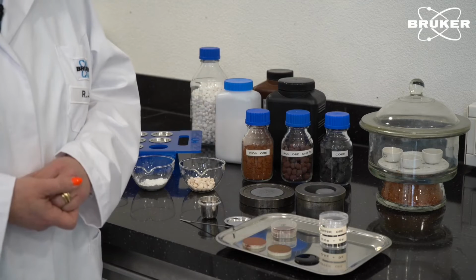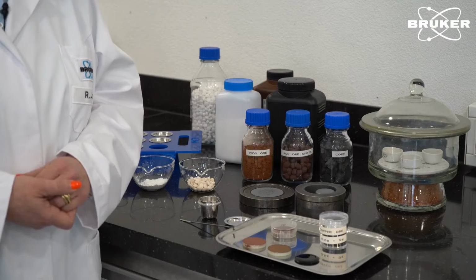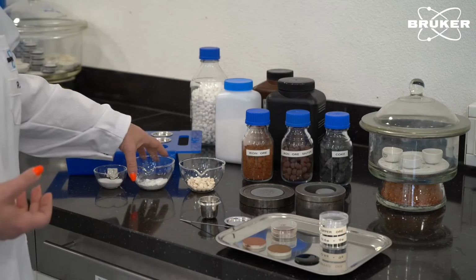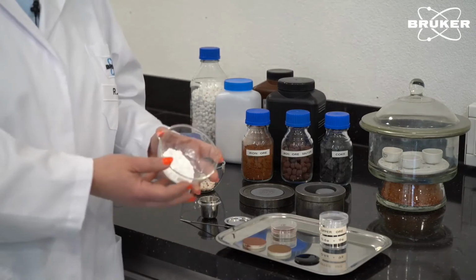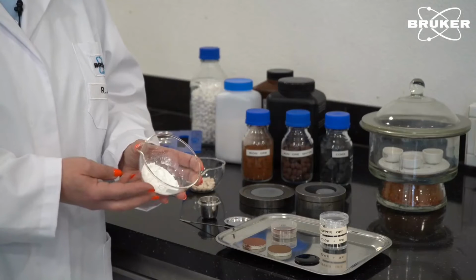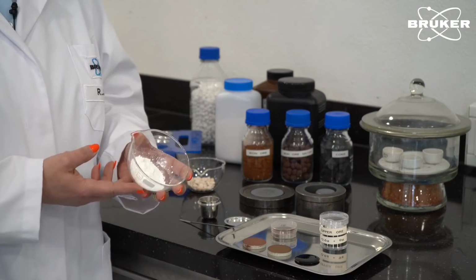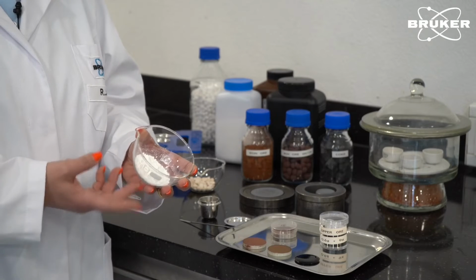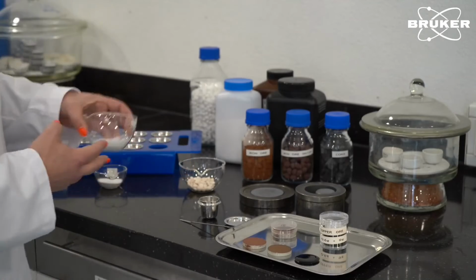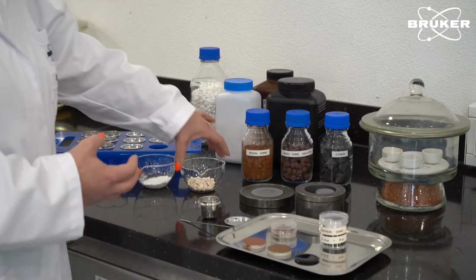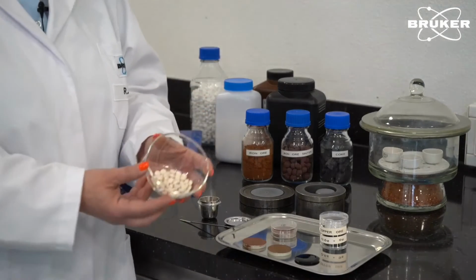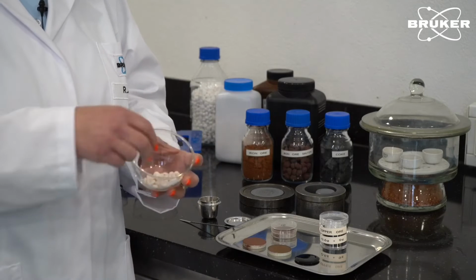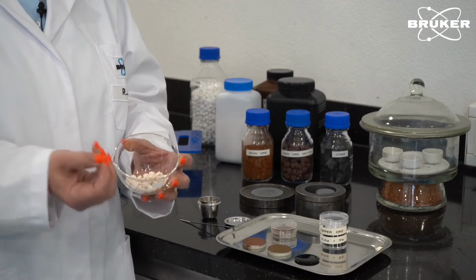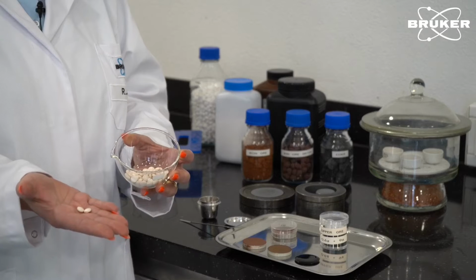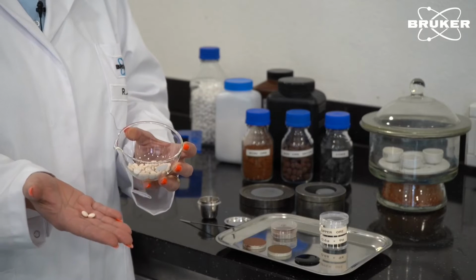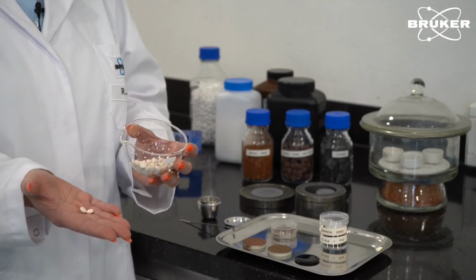After the material is ground, you can mix the sample. Here in our lab, if I prepare a pressed pellet manually, typically we use some wax, which is diluted 1 to 10 into the sample and can then be pressed very easily. If an automation unit is used, then typically you will have this kind of grinding aid tablets, which are just added to the material, maybe 2 or 3, depends on the recipe, and then the sample is ground with the binding tablets and a pressed pellet is prepared.